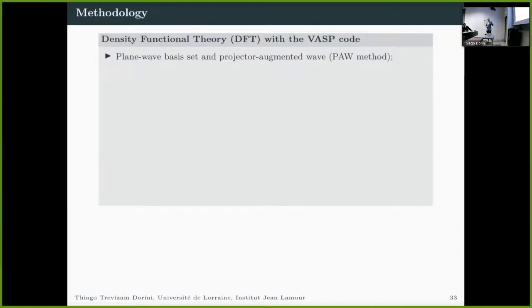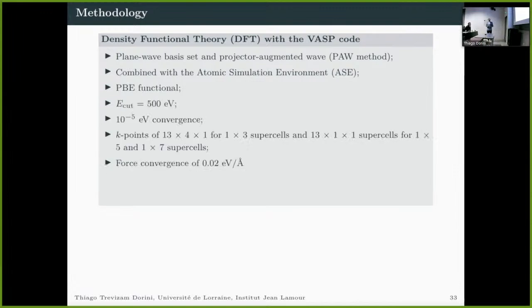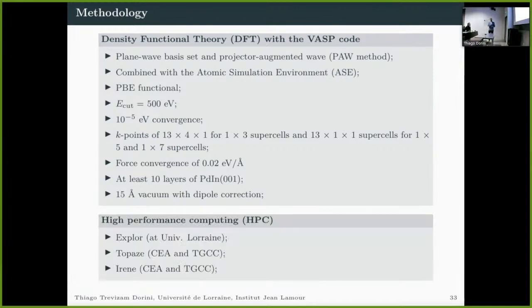For the second part, we have also used density functional theory with the VASP code, combined with the Atomic Simulation Environment. In this case, we used the PBE functional, and these were the characteristics of these calculations. We modeled the substrate with 10 layers of palladium indium 001, and used 15 angstroms of vacuum with the dipole correction. We used three supercomputers for these calculations: Explore, Topaz, and Irene.